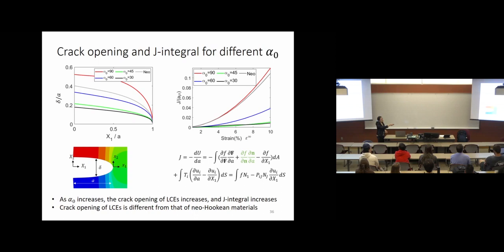Then on the right-hand side, I'm further calculating the J integral, which means how much energy is released when you have a crack increase per area. When we calculate the J integral, we can find that because the free energy is different from other typical rubber, we have an extra term because of director rotation. But if you reorganize this form, the final form we obtain is still similar to a typical J integral for a rubber material, because the material anyway is elastic, right? Hyperelastic material. There's no energy dissipation. Therefore, the J integral can still recover the typical form.